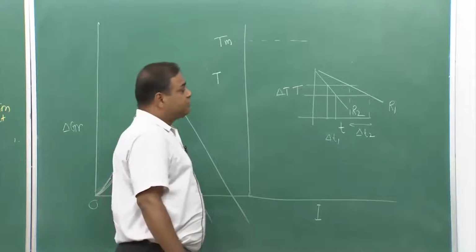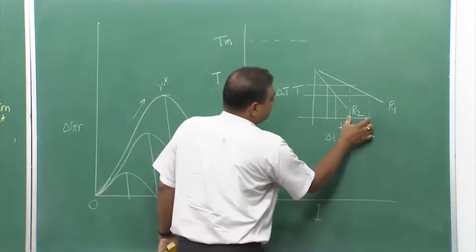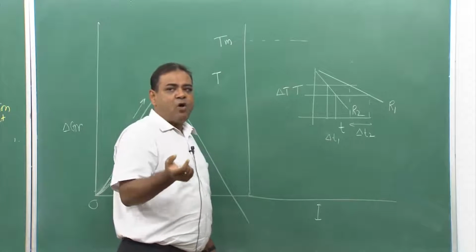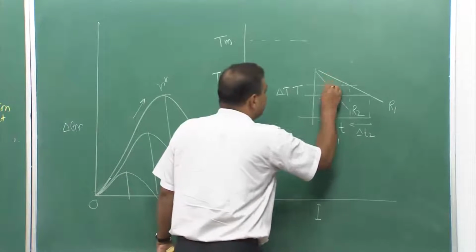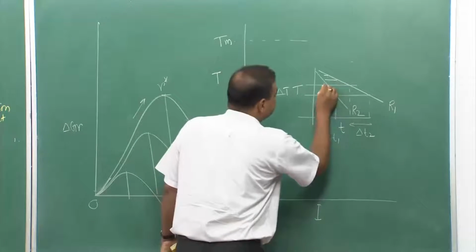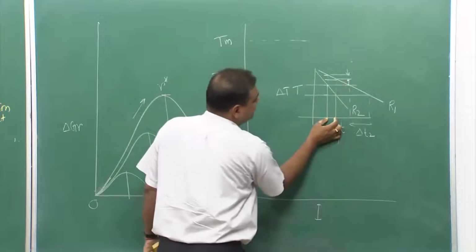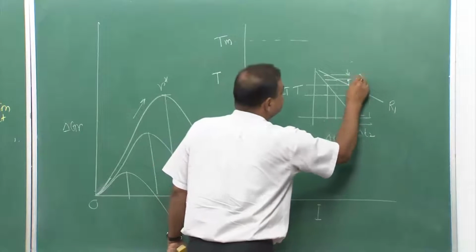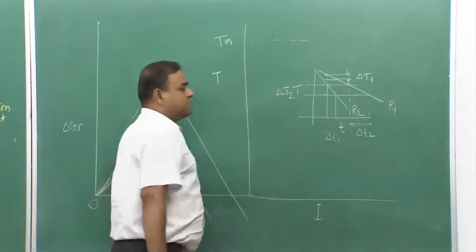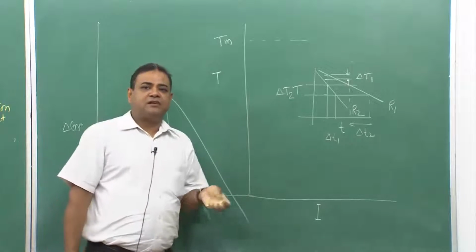is slow. So, in other way, let us say I fix my duration, this one I have fixed. So, I would like to see in a similar time duration how much del T I can achieve. So, now if I go there, here I am achieving this much, but here I am achieving this much. So, this del T is this one. If I try to follow the same duration, this much is the del T1 and this is del T2, in case of higher cooling rate. So, that means higher cooling rate gets me higher del T, that means higher undercooling.